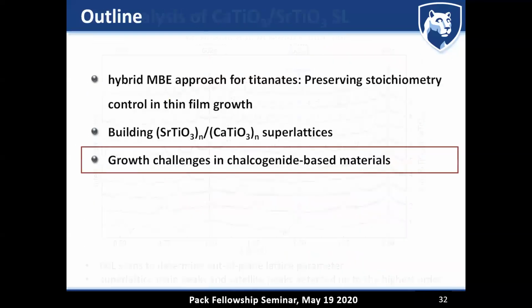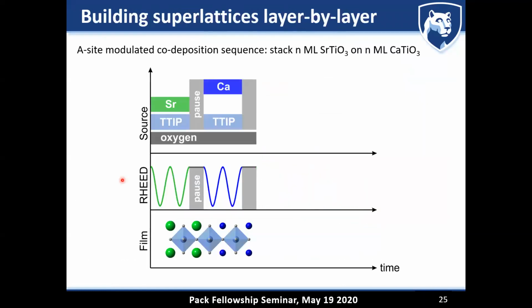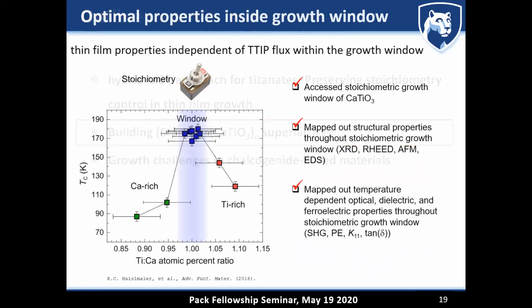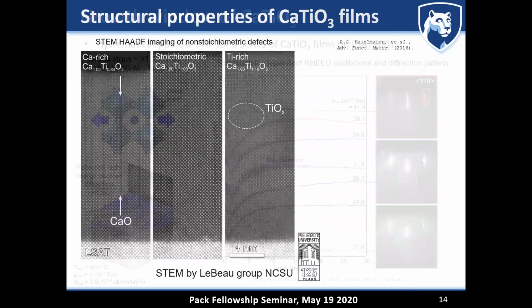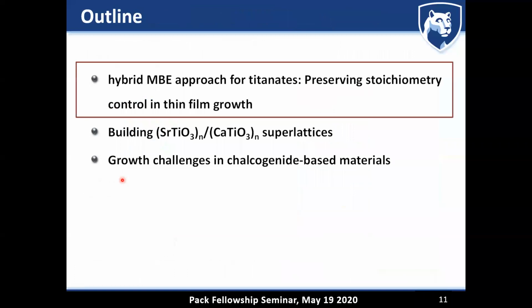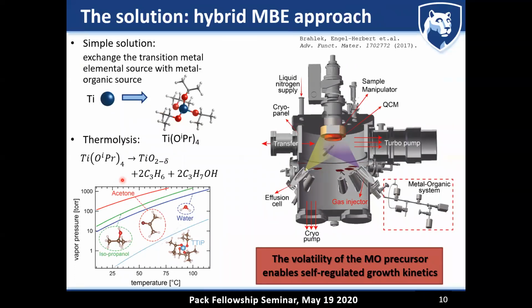So this is an idea that goes back to looking at how people grow complex oxides. If you limit yourself to molecular beam epitaxy and metal organic chemical vapor deposition, and let's say you want to grow strontium titanate, in this case it was calcium titanate, but for strontium titanate it's the same. The pain point of molecular beam epitaxy is actually the titanium. It's really hard to evaporate as it has a fairly low vapor pressure, and it also reacts with the crucible material. But strontium is no problem. Strontium you evaporate at 450, never gives you any problems.